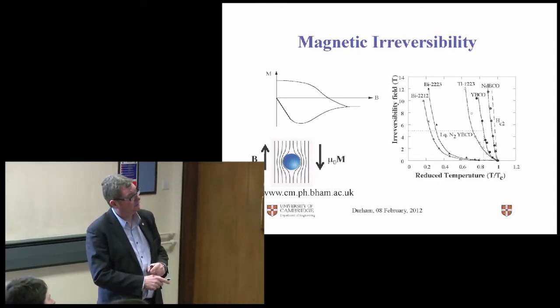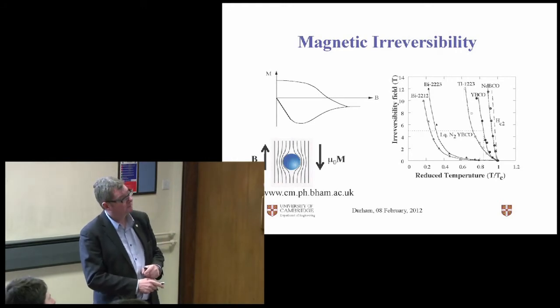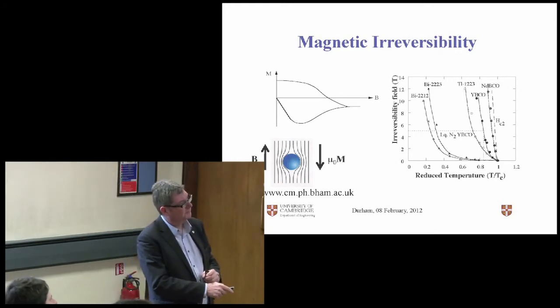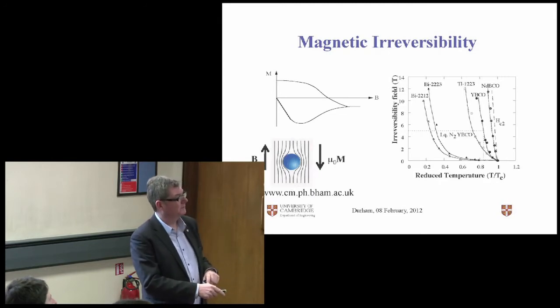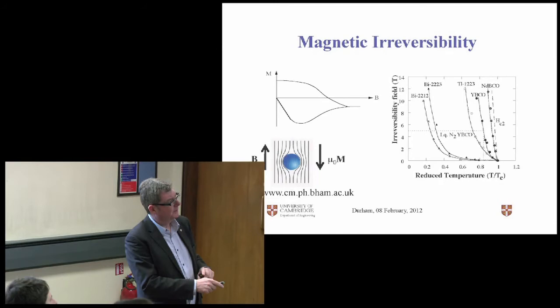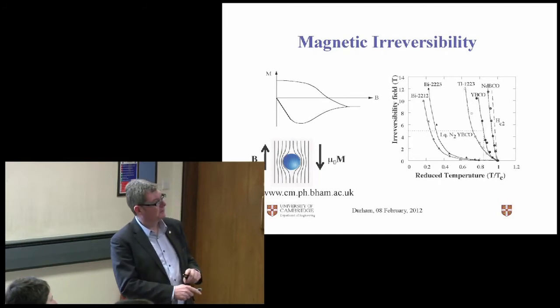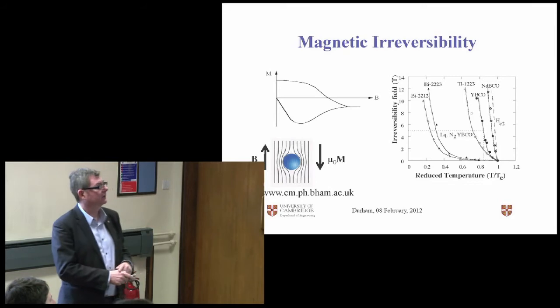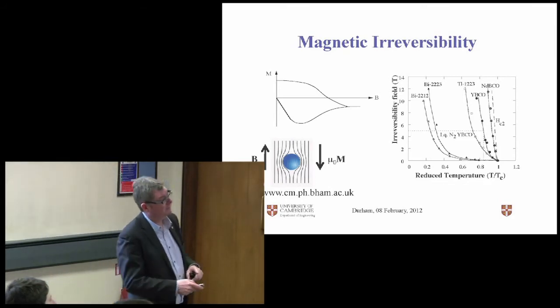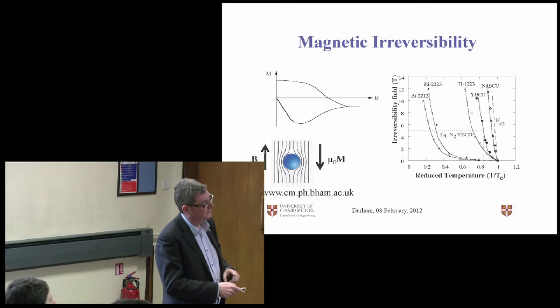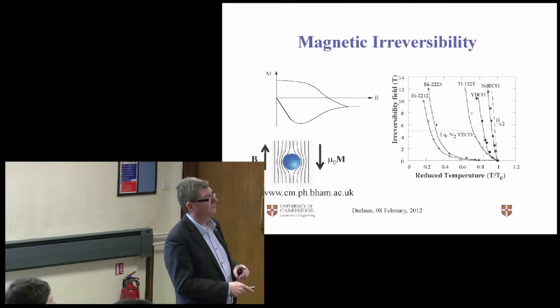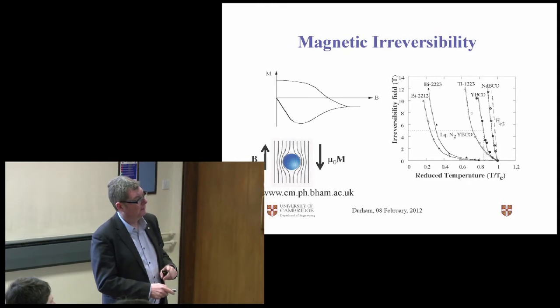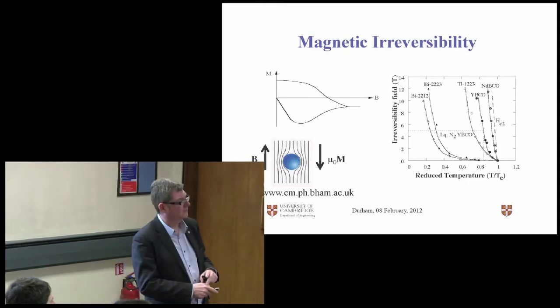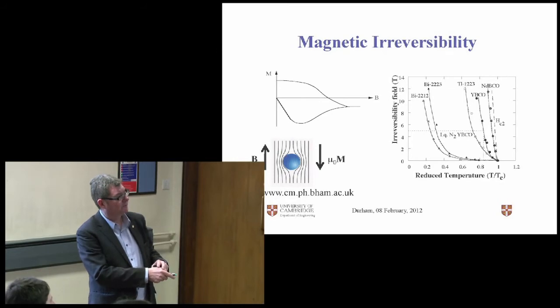And as we go to lower temperature, this point moves to the right. So this plot here shows how irreversibility field, this pinch-off point, varies with temperature. And you can see we can define a line, and we have the different high-temperature superconductors here. The bismuth-based materials, which have a TC of between about 90 Kelvin and 110 Kelvin, have a fairly low irreversibility line, whereas the rare earth-bearing cuprates have got this high irreversibility line. HC2 represents the limit above which the material is not superconducting.